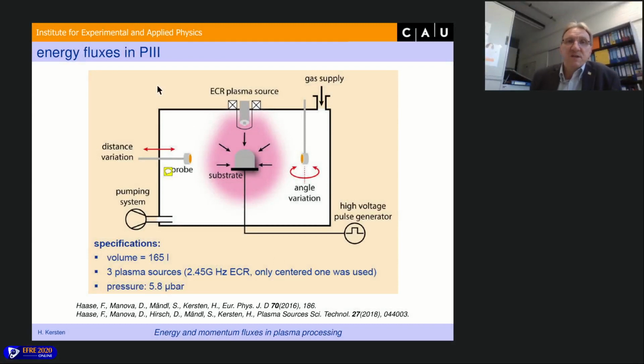Another example is PIII, plasma ion immersion implantation. And here you have your substrate. It's a cathode of a glow discharge. There is a glow discharge surrounding. In this case, the discharge was generated by an ECR plasma source. And far away, we put our probe. So we could move the probe and circle the probe to measure the angle distribution.